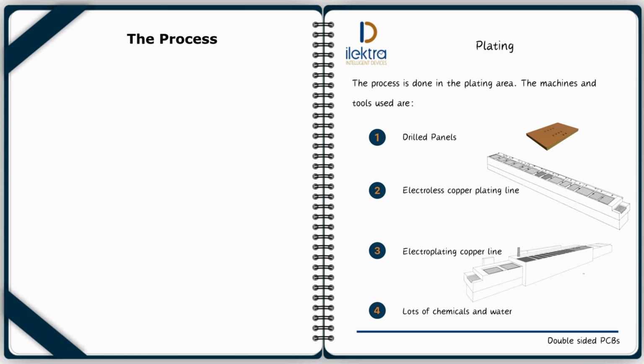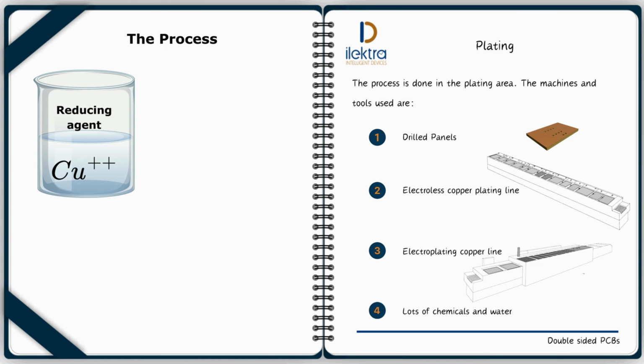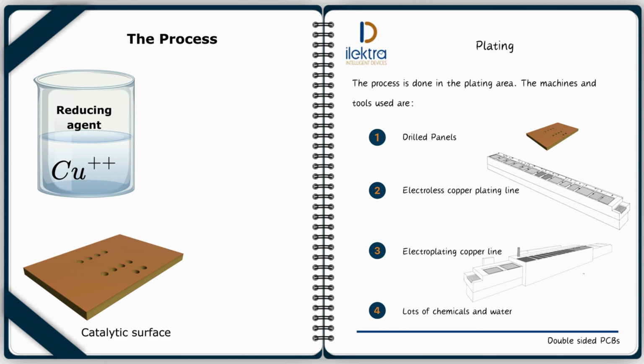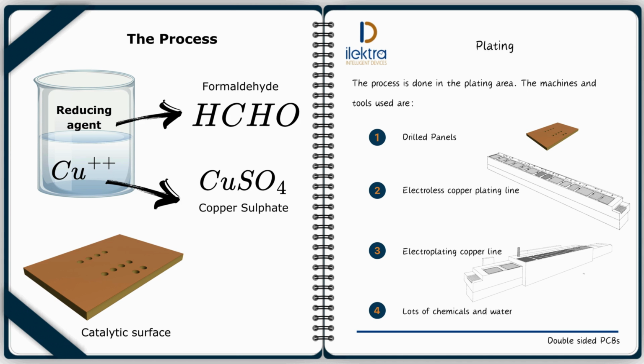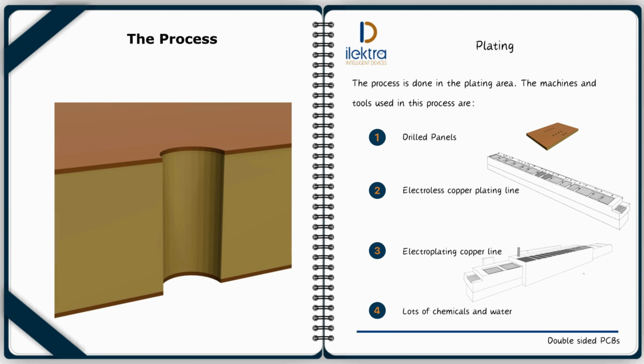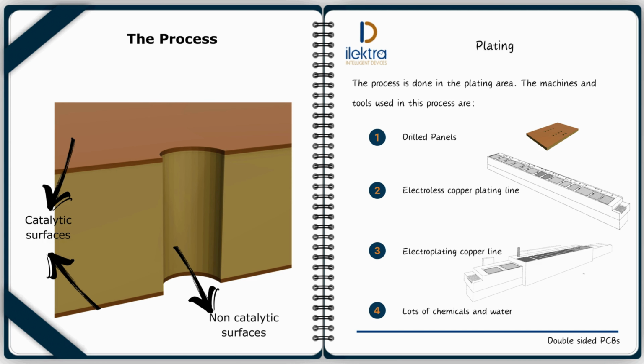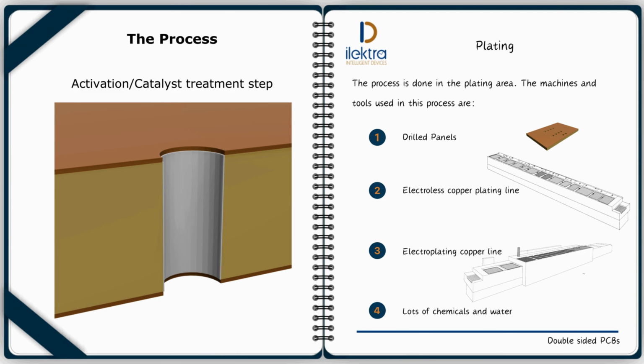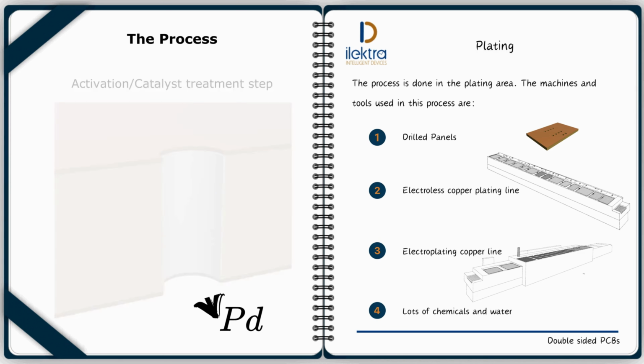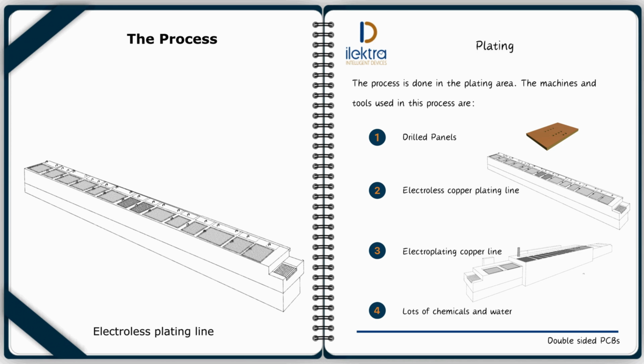Electroless plating is an autocatalytic immersion plating process. For the autocatalytic chemical reaction to take place, we need an aqueous solution of positive copper ions, a chemical reducing agent and a catalytic surface. In the plating bath, the copper ions are provided by copper salts like copper sulfate. The reducing agent, usually formaldehyde, donates electrons to the copper ions, reducing them to metal atoms that are deposited on all catalytic surfaces. For PCBs, the copper sheets are catalytic in nature, but the dielectric core is not. Thus, the activation or catalyst treatment step is needed to coat the surface with a thin film of a catalytic precious metal, like palladium. Now, let's have a look at the electroless plating line.